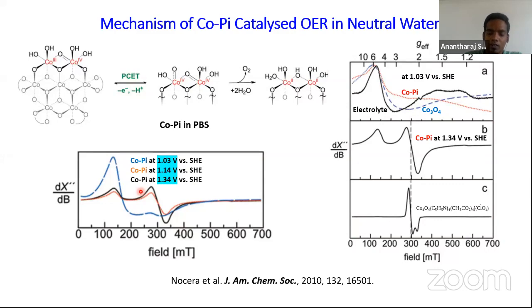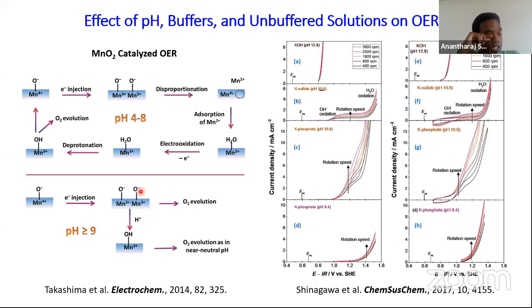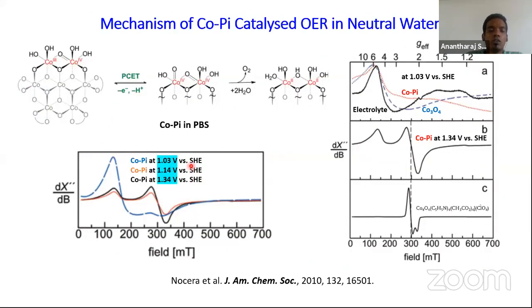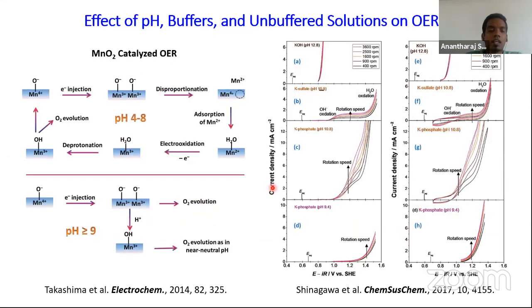So this shows us that mechanisms of any electrocatalyst can be revealed using very old and well-established spectroscopic techniques that we have. But recently, spectroelectrochemical techniques are gaining huge attention, because all those experiments I have shown here were done with electrolytes that were frozen after the experiment. But now we can do such experiments while running the electrochemical measurement, and simultaneously we can acquire an EPR spectrum or any other spectroscopy that you wish to use.